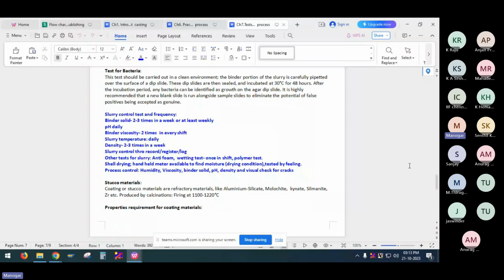Other tests for slurry that can be followed are anti-foam and wetting test, once in a shift, and polymer test. For shell drying, a handheld meter is available to find moisture, or dry condition can be tested by feel. Process control in the shell coating area is control of humidity, viscosity, binder solids, pH, density and visual check for cracks. These are the process control points in the coating area related to slurry coat.